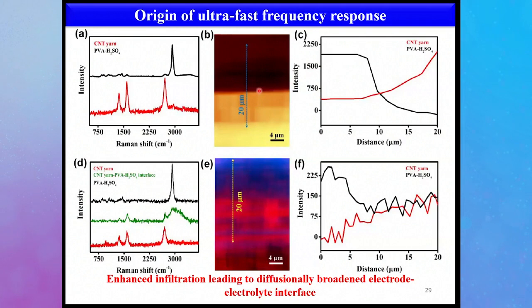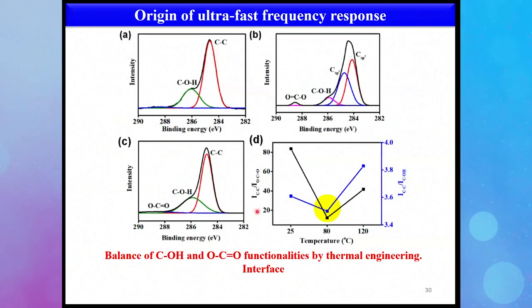That is one. Now, I didn't discuss this, but we have done XPS, X-ray photoelectron spectroscopy, at the interface as well, which is given here. It is also given in the paper. So here, basically, what the annealing does is it creates carbonyl functional groups at the interface, and this actually assists in seamless charge transfer across the interface, which is important for ultrafast capability.